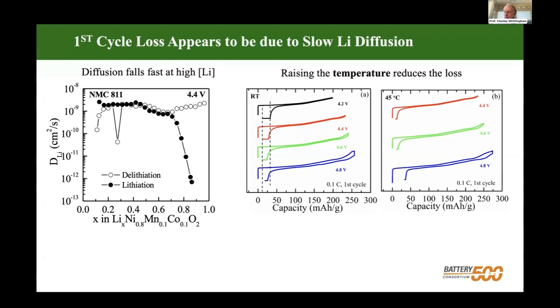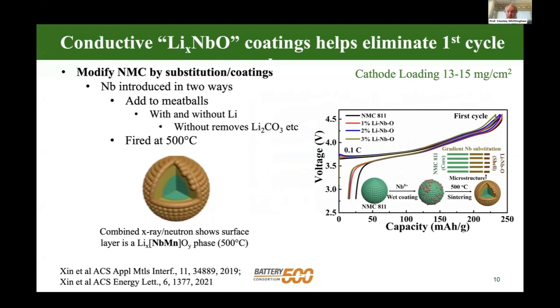And the way we opted to do it was to modify the surface and the bulk of it. And we chose to modify the surface by using niobium. And why we chose niobium is because lithium niobium oxides are known to be good ionic conductors. So this is essentially putting an electrolyte kind of surface on these materials to protect the surface. And depending on what temperature we use, depends on whether we get surface diffusion or bulk diffusion.